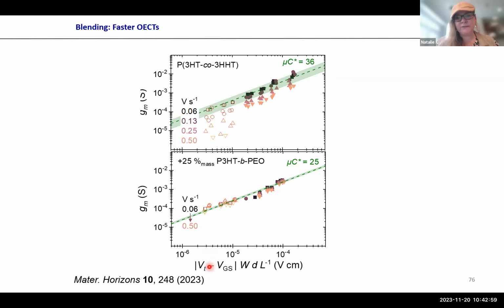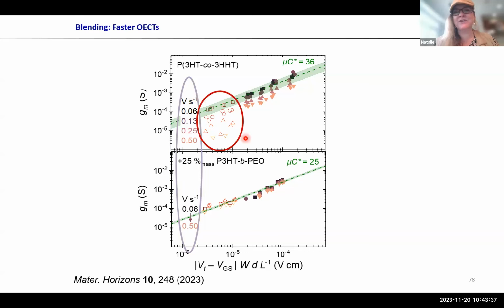And if you look at this graph here, I think that could eventually also be important for specs. I mean, it's different applications. When you look at how the key parameter like transconductance works when you change transistor geometry. So here you have bigger devices versus smaller devices. In a nice theoretical world, the geometry of the device should not matter. It should also not matter with the rate that you measure, but you immediately see larger devices, which are obviously easier to fabricate than the smaller devices, where you have to go to lithographic approaches. They do not scale, and you really have a large scattering of your data with measuring speed.